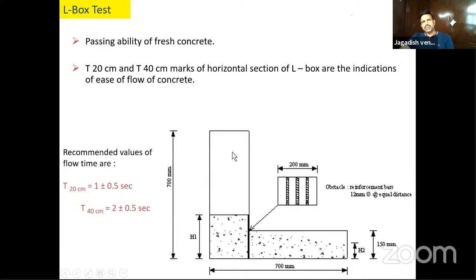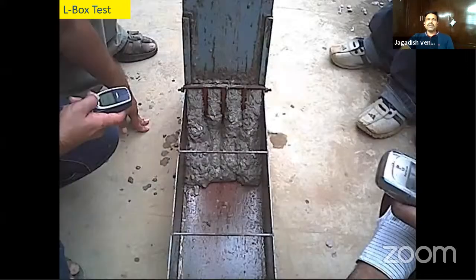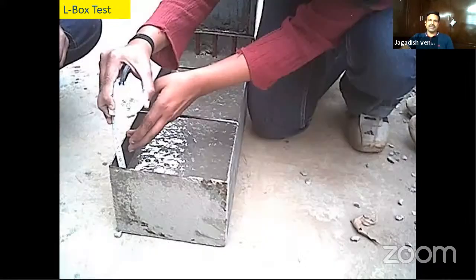So here you measure two things. You can measure the time taken to reach 200 mm and 400 mm horizontal box dimension. Our total horizontal box dimension is around 700 mm. So you measure from the vertical box. You can measure the time taken to reach at 200 and time taken to reach at 400. The recommended value is also there. But what you measure is the blocking ratio of the concrete.